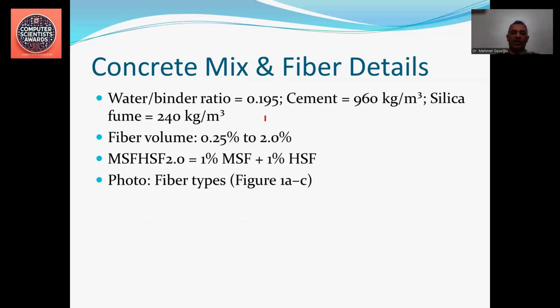The water binder ratio of the concretes is constant at 0.195. A cement content of 960 and silica fume of 240 kilograms per cubic meter respectively have been utilized. The fiber volume was changing from 0.25% to 2%, and for dual use of fibers, for example, the designation MSF, HSF 2% means 1% microsteel fiber and 1% hook steel fibers are incorporated in this mixture.